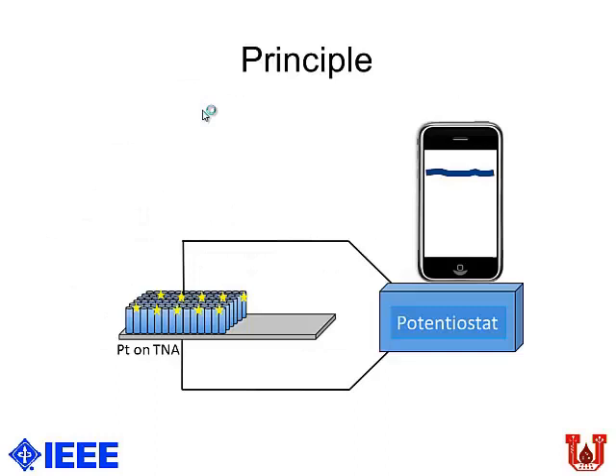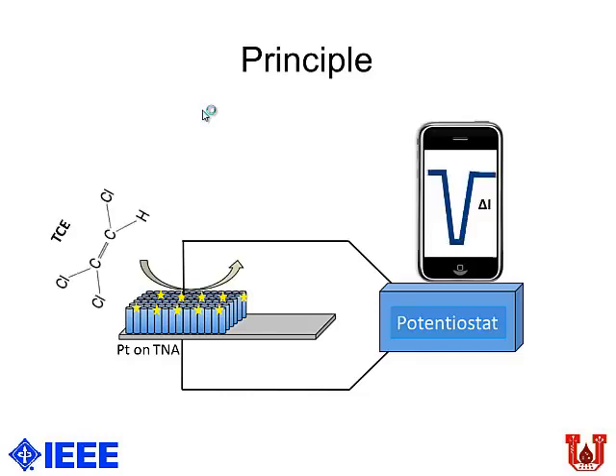You have titanium nanotubes right there on a titanium metal substrate. The golden thing is your platinum functionalized on the nanotubes, and then you have a potentiostat readout. So basically, when your trichloroethylene reacts with your sensor system, you get a change in current, as simple as that, and that is indicative of the presence of trichloroethylene.